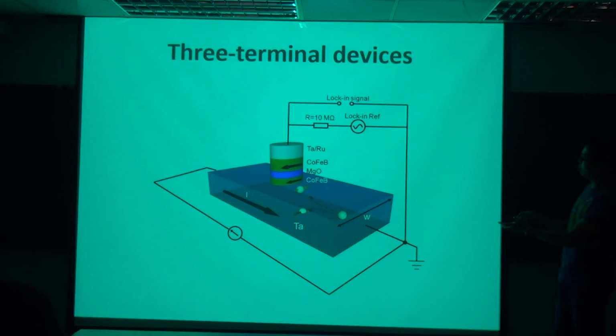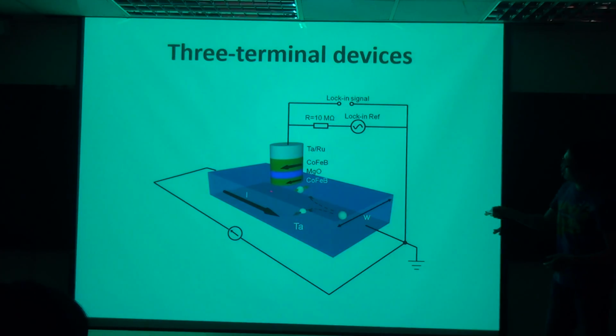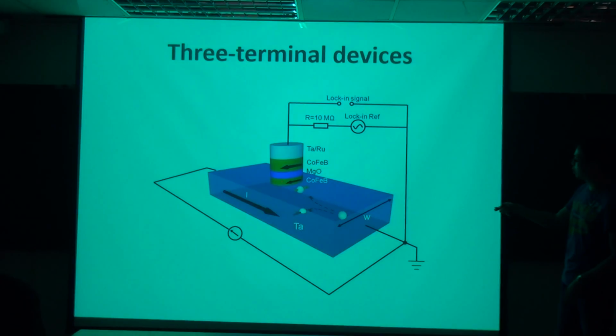And so here comes the three-terminal device that I just mentioned. It's much simpler than the three-terminal device that I mentioned earlier, which is a combination of a tunnel junction and a spin valve. So now you just have a tunnel junction on top of your tantalum layer. So the tantalum is your source of generating spin, and you just send a current through this tantalum channel, and then you will inject spin through the spin Hall effect into this cobalt iron boron layer, and then you can switch the magnetization of this layer through the spin Hall effect.